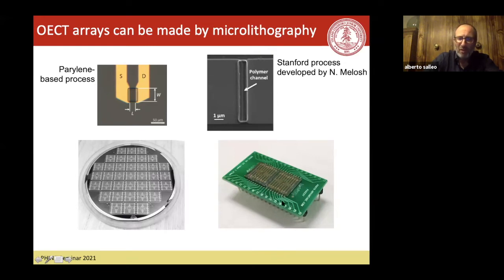And so now you can see here all these pinouts, you can imagine having 10 or 15 of these sensors. And this also becomes important when you want to be more quantitative, because you'll always want to have some dummy devices, some reference devices. Because remember, I told you, you sense by looking at how many cations come from the electrolyte. But if the electrolyte changes concentration over time, that will change as well. So you'd always like to have some dummy devices that essentially measure the conductance of the electrolyte. That way you can take that into account in your measurement, in your calibration curves. So to turn this into a real sensor, it's actually quite a bit more complicated, but being able to have a lot of devices near each other helps a lot.